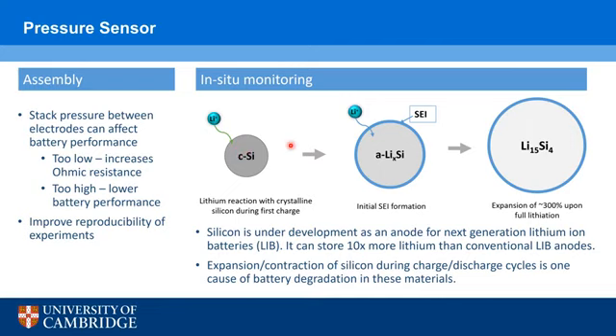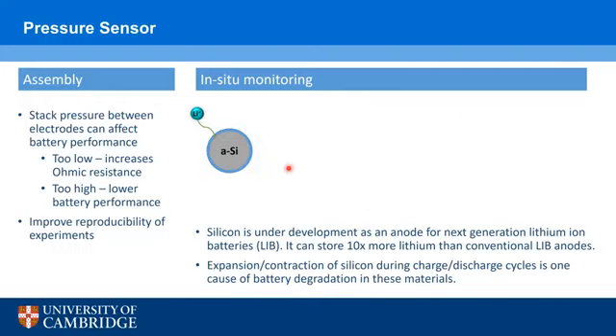of lithium-ion batteries using this material. However, it's not without its issues. So when you lithiate silicon in the first cycle, it can expand by up to around 300%. And at the same time, at low voltages, we get this degradation of the electrolyte that forms this SEI layer, or solid electrolyte interphase layer, on the surface of the silicon. And then when we delithiate the material, the silicon then shrinks back to not quite its original size, but it shrinks. And then in subsequent cycles, when we relithiate the silicon, it then expands again.